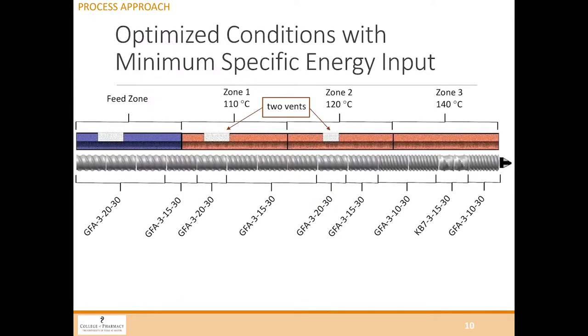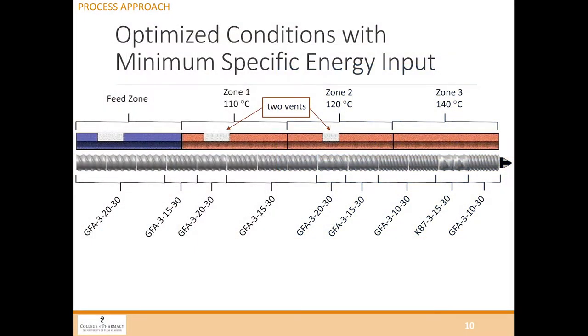Okay? And so if we just look at it from a processing perspective, we can't really totally avoid degradation. So this is the best we can do with the process. We have two vents. We're trying to purposefully remove moisture from the compound. Okay. And here's the extrusion, with the kneading elements. So basically, most of the drug is dissolved here. Once it dissolves, we're trying to get the drug out of the extruder as quickly as it can.